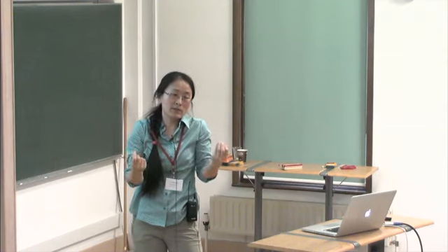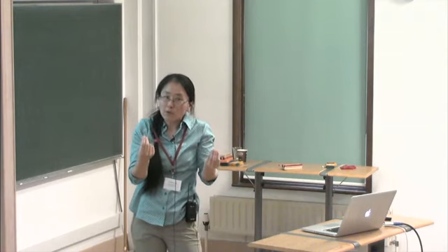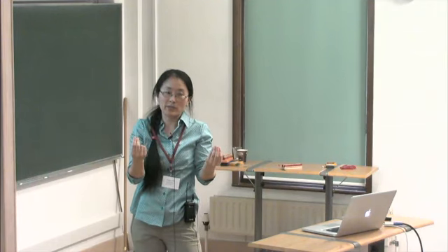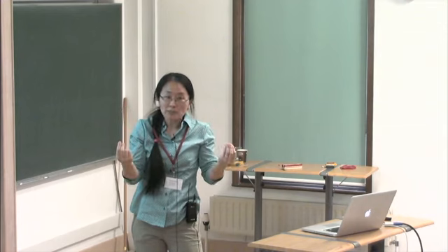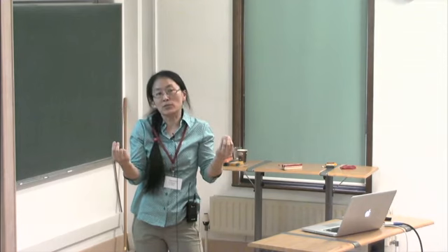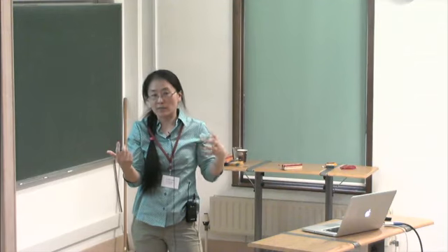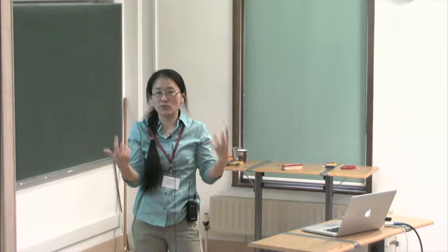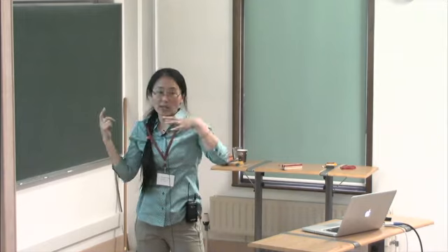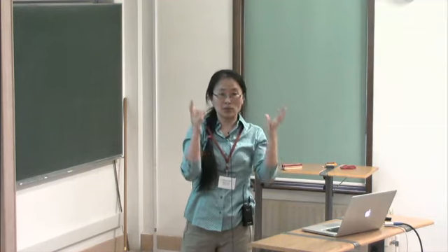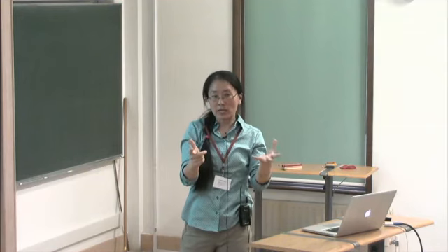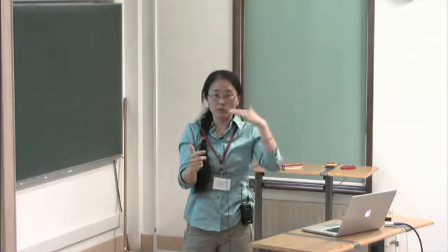Our reasoning is, if you have more than 1 pixel, we should start to see some. We tried to do a partitioning and say only a fraction of melt, but it turns out this computation is really intensive. So we just say, anything we don't see, add 1 pixel of melt. You're going to change the conductivity some, but you don't change the relations. And you don't change the permeability at all.